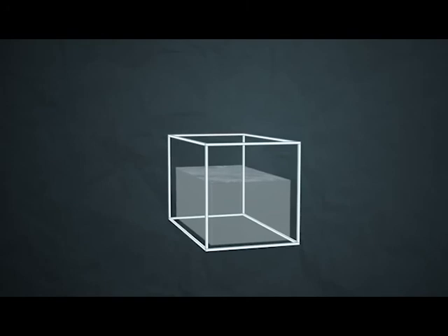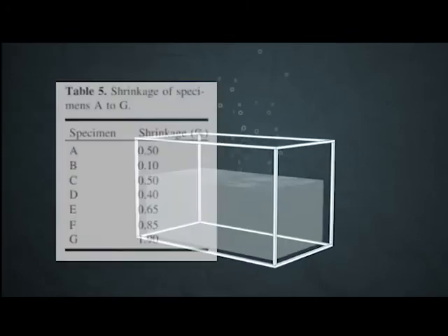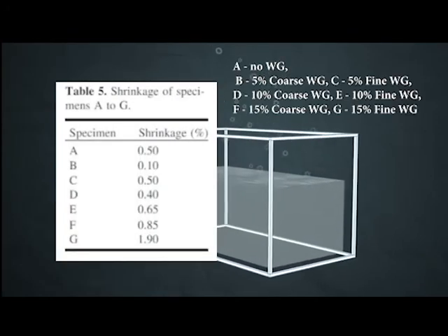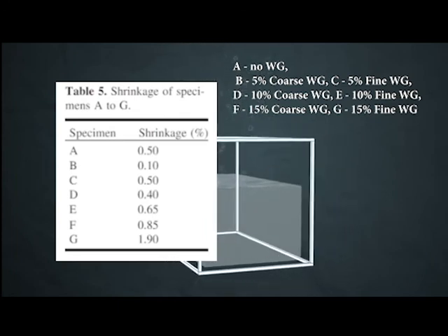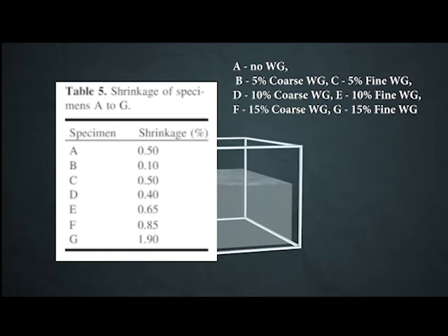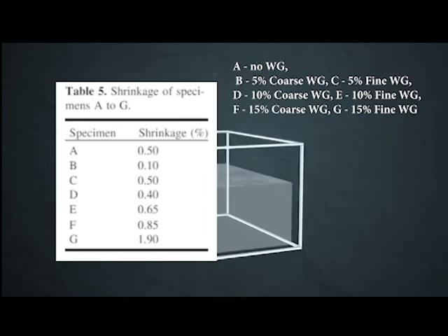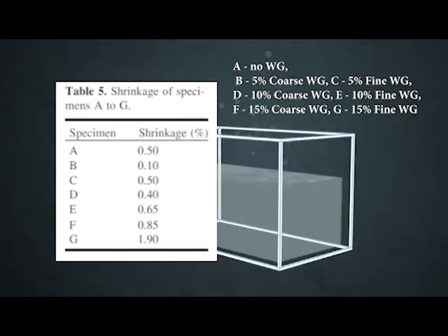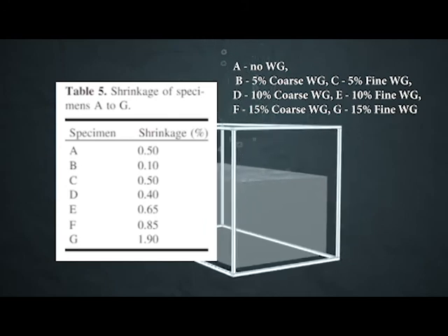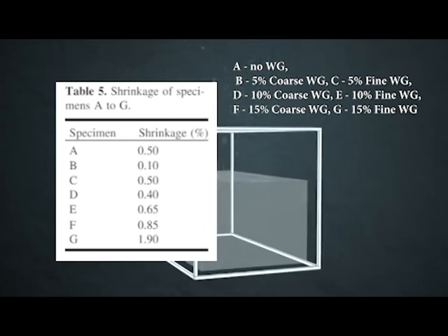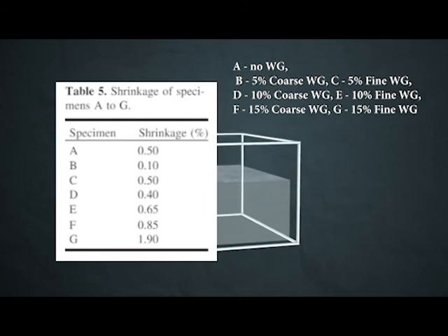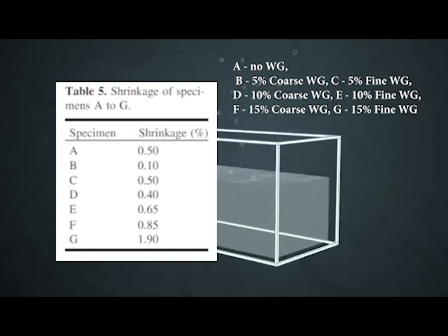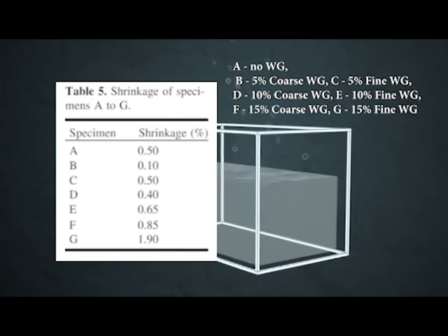In a similar research, it was stated that the 5% additive waste glass had no statistical improvement on clay bricks firing shrinkage, while 10% waste glass had only a slight increase if the particles were coarse, but had a significant difference if it had finer particle sizes. The table shown on screen are data from the research conducted by Chidiak S.E. and Federico L.M. 2007.